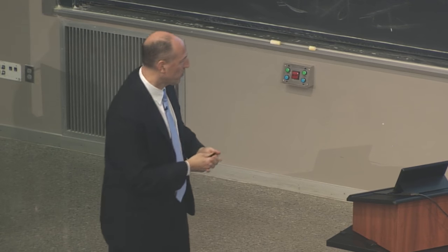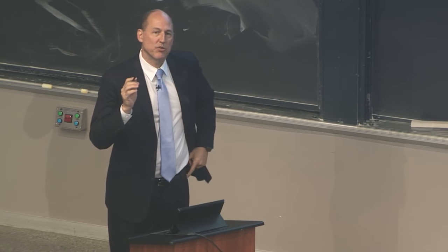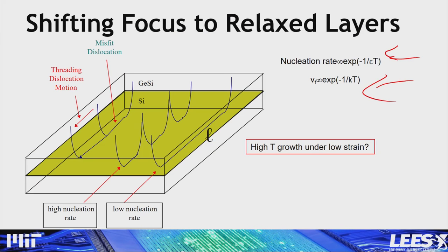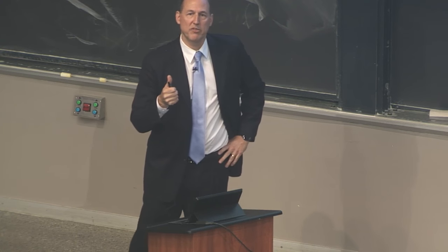So the first idea we had was, well, I have to have these threading dislocations coming up, but you can remember I told you that this length here is what relieves the stress at the interface. Here I have the case where the amount of misfit dislocation length is the same. But in this case over here, I've nucleated 3 dislocations, and I have many more threading dislocations to deal with. Whereas if I use the feature that it's difficult to nucleate, which I proved in grad school, then if you could get this thing to propagate further, you could have much more strain relaxation but have fewer defects coming up to the top.